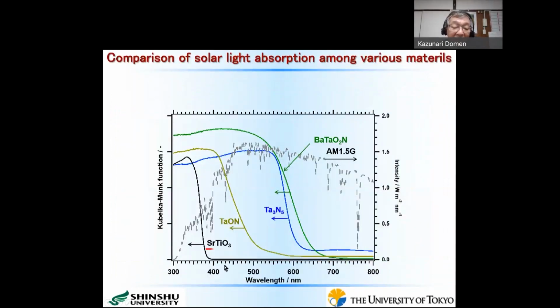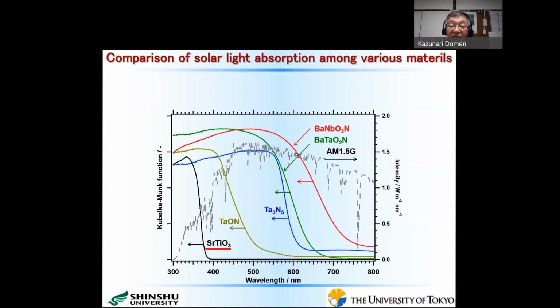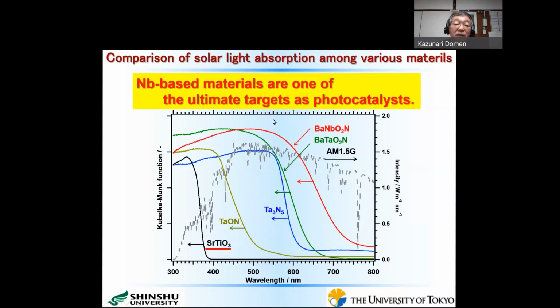Okay, at first I discussed strontium titanate, but as I said, this material absorbs only UV light. Then here I show the tantalum-based photocatalyst as shown here. These materials absorb very well the visible light region photons. However, if we look at the niobium-containing photocatalyst, as you see here, these materials absorb almost all parts of the visible light region photon. So the niobium-based materials are one of our ultimate targets as photocatalysts.